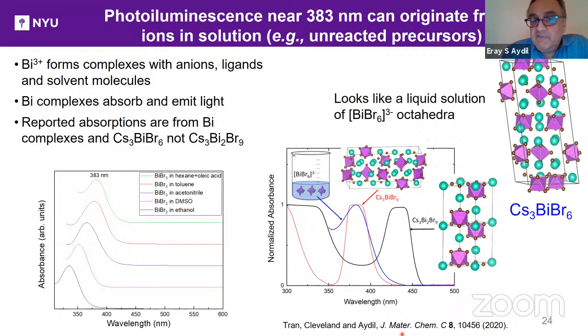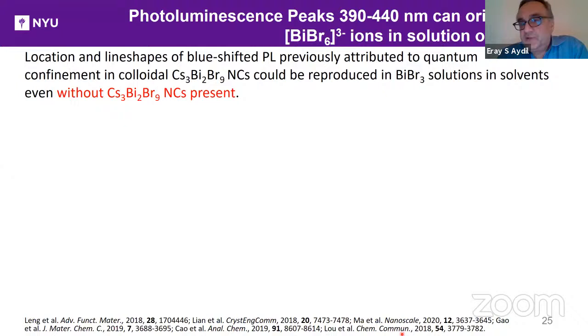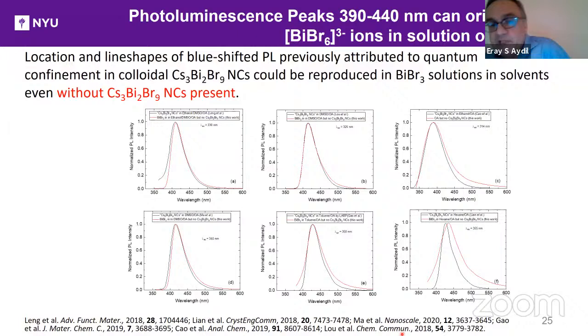In fact, we did this with photoluminescence. The blue shifted photoluminescence previously attributed to quantum confinement in colloidal cesium-3 Bi2 Br9 nanocrystals, we could reproduce with just BiBr6 solutions in solvent without any nanocrystals present, both in line shape and in location. And here they are. These are six different papers. All we did was digitize their data and normalize it, and then make their solvents and put the ligands that they used in there, excited at the same wavelength as they did. And we can reproduce the line shapes, and there are no quantum dots in our solutions.